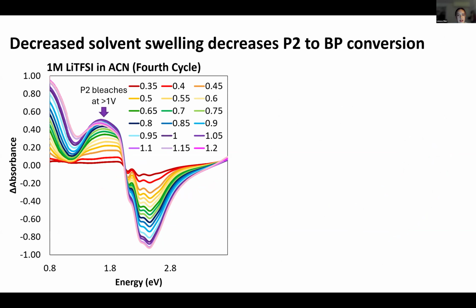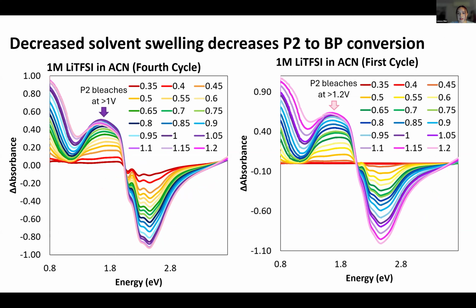And so I wanted to investigate and see if this would change if we doped on the first cycle when the film is not swollen at all. And in fact, it did change, and now the P2 peak begins to bleach at a much higher potential than when we were doping on the fourth cycle. So this is confirming our theory that swelling is having an effect on the conversion of polarons to bipolarons.